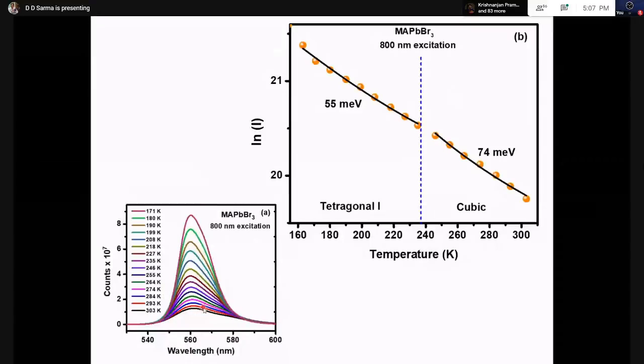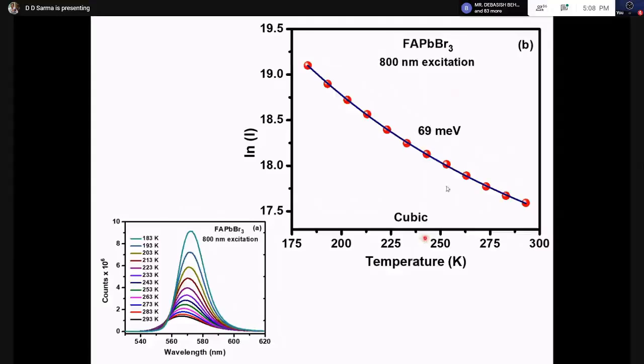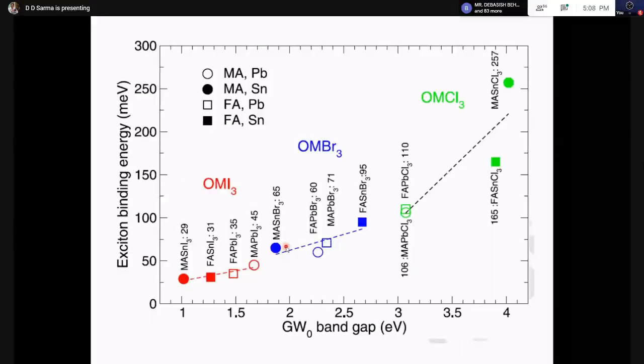You can do it on MAPbBr3 when it has a crystal structure change from cubic to tetragonal. You can see also the excitonic binding energy changes across it. You can do it for FAPbBr3 and others also. In fact, together with the Vienna group, we had long time back calculated the excitonic binding energy for all useful materials that were being talked about at that time.